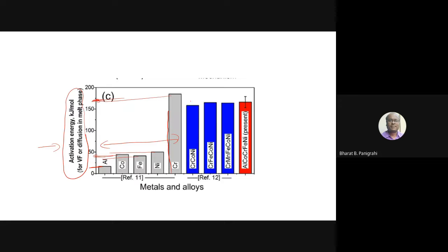What you see here are for the high entropy alloys, when they form near their melting point, and they have their viscosity in this range. Their activation energy of viscosity is in this range. And in our alloy, which is the red color, when you measure the coefficient of viscosity, it exhibits the activation energy in the same range. It says that whatever phases we are predicting here, the liquid phase which has formed has a coefficient of viscosity exhibiting the activation energy reported for this high entropy alloy.